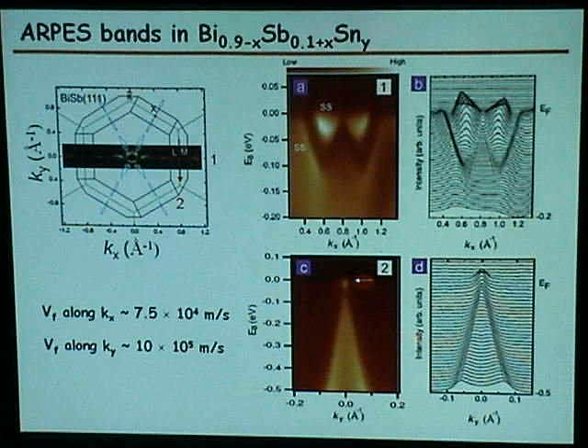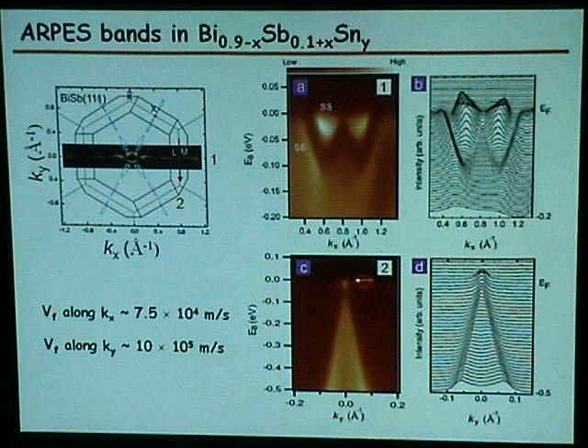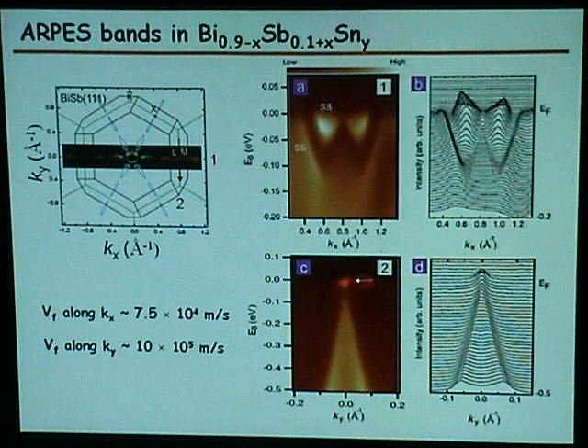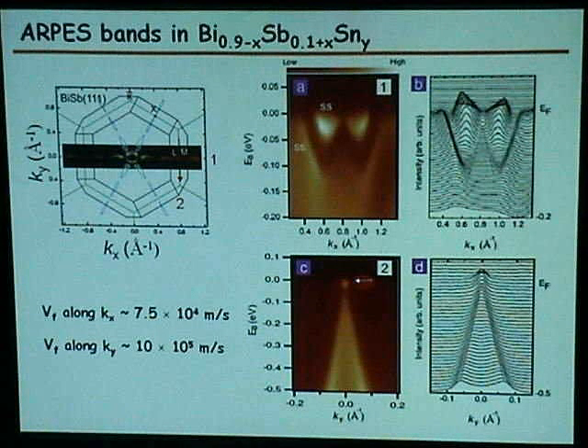Now, I suggested to my colleague that we suck some electrons out of this system, so we'll get a Dirac point. So he tried that, and we repeatedly measured the samples, but we can never get rid of this thing. So in other words, it's something else. It's not doped electrons in a graphene-like band structure. It's something else. But this linearity is quite remarkable, and somehow it has the graphene-like velocity.